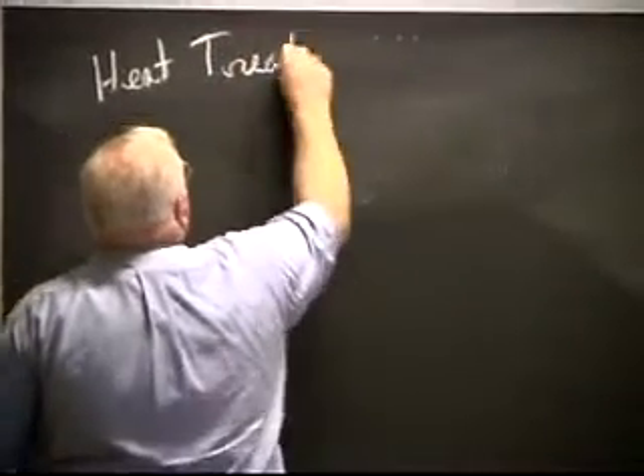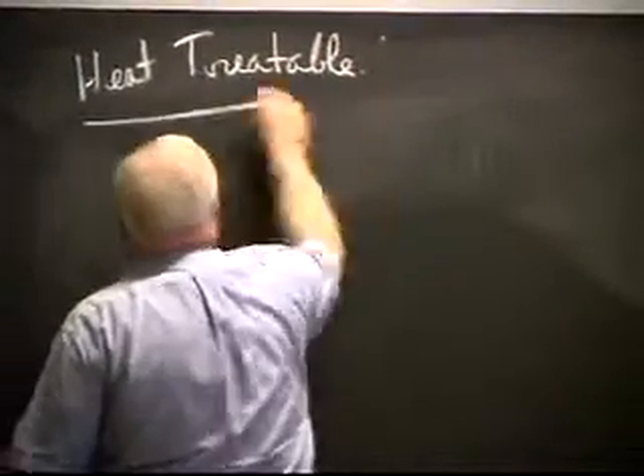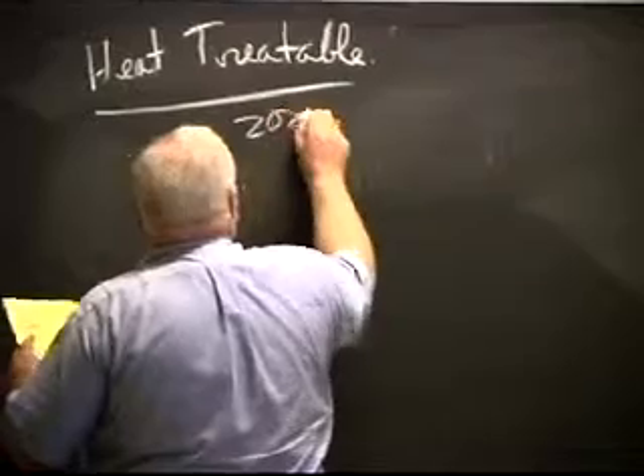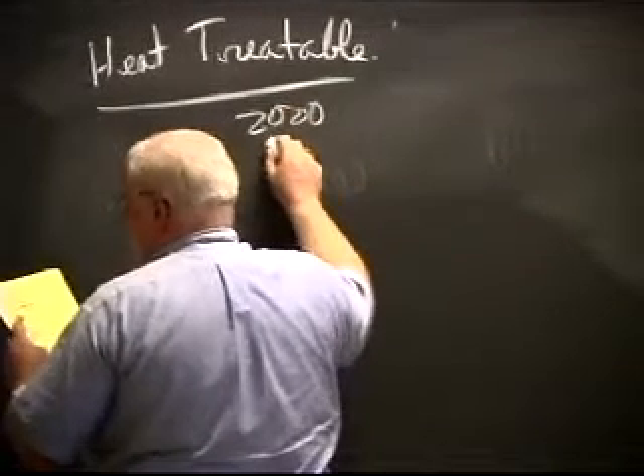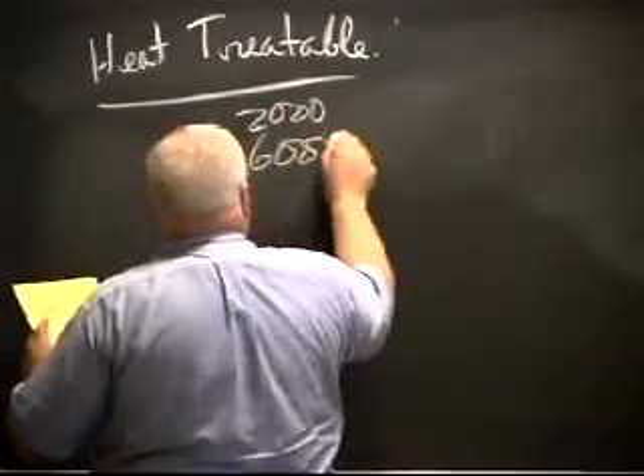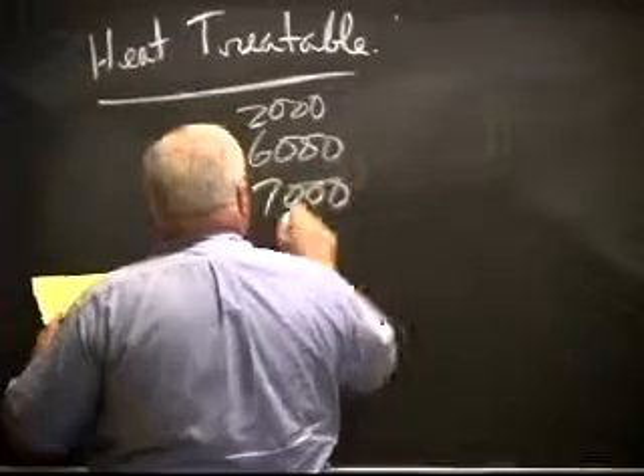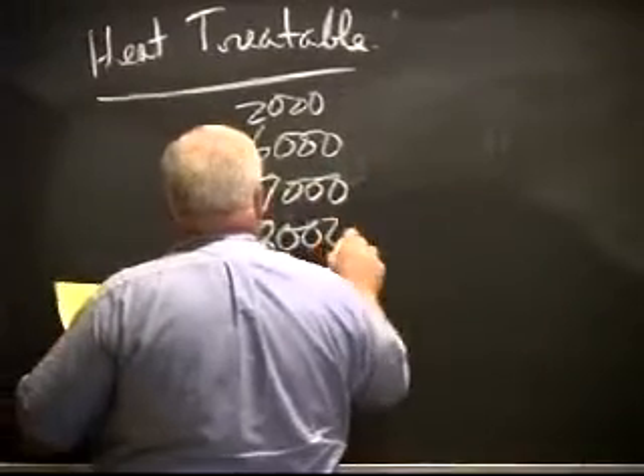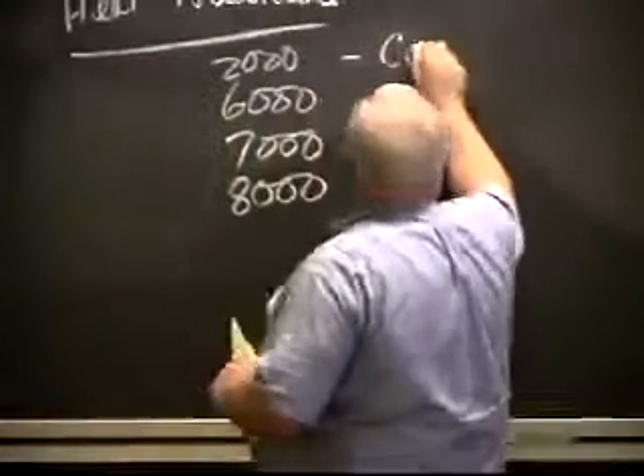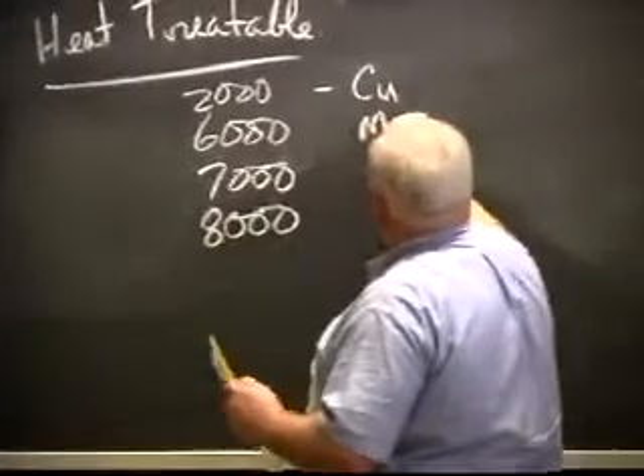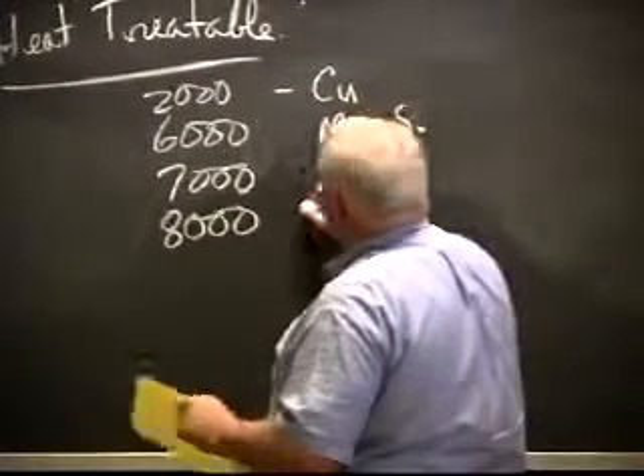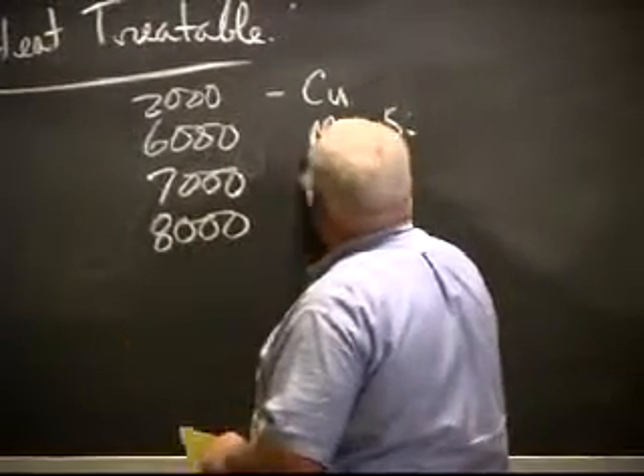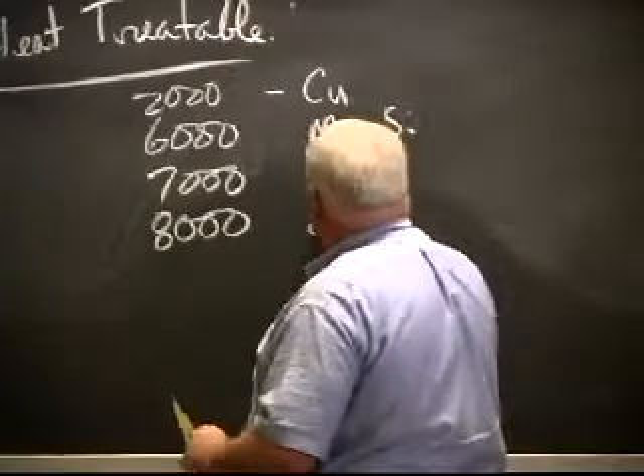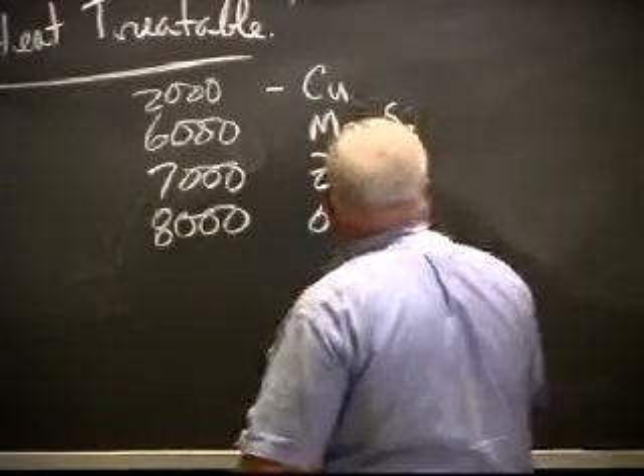In the heat treatable alloys, we have the 2000 series, the 6000 series, 7000, and the 8000 series. These are copper-based alloying, magnesium plus silicon, zinc, and this 8000 series is just other, everything else.